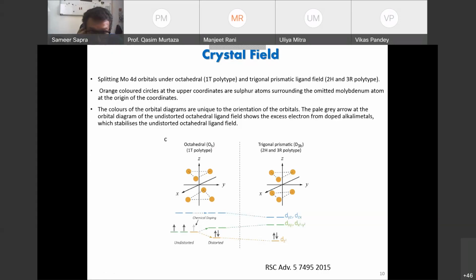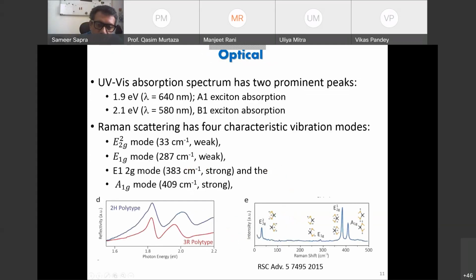Now, when you go and make these materials, you need to characterize them. And some of the characterization tools, one of the easiest ones is UV absorption spectroscopy. And all of these semiconductors, you would see these two peaks, the A peak and the B peak. Okay. In case of molybdenum sulfide, it's at 640 and 580 nanometers, or 1.9 and 2.1 electron volts. Okay. So you'll see these two peaks clearly.